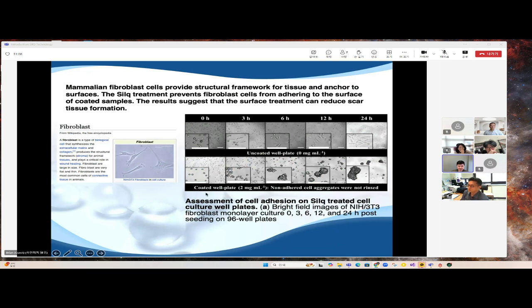With our surface treatment, again on the bottom, those circular cells don't elongate, they don't anchor to the surface and stick. They actually stick to themselves. They have nothing to stick to because that surface is protected by the coating. And we have good indication that we can resist things like the foreign body response. When you put a silicone or other type of material in the body, your body responds to it in a certain way. We have good indication that we can resist that response, which may be good for your cochlear implants that may lose signal over time.